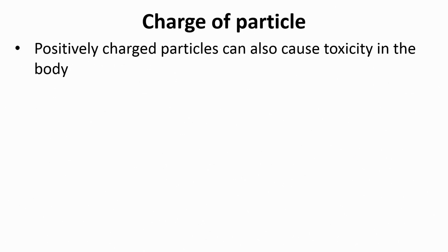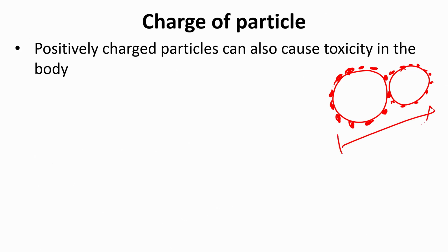So, positively charged particles can also cause toxicity, because they tend to adsorb so much. If I have a positive charged particle, there will be lots and lots of protein that will get adsorbed on the surface, and the structure of the protein will change, the function of the protein will change, the way these guys can coagulate with another particle and so on and so forth. So, their actual size once it goes in the blood may change and it may cause toxicity. Maybe it will become larger than 5 micron, maybe this will become 10 micron, and that will clog blood vessels,